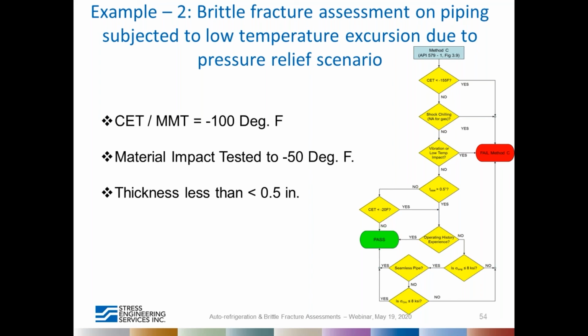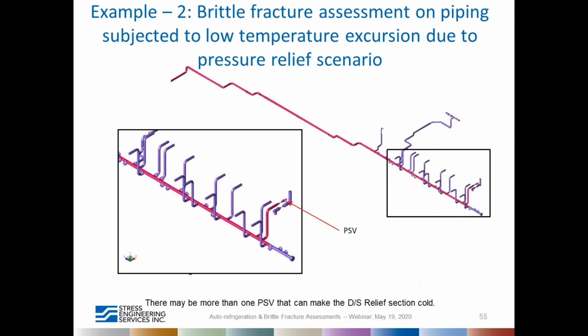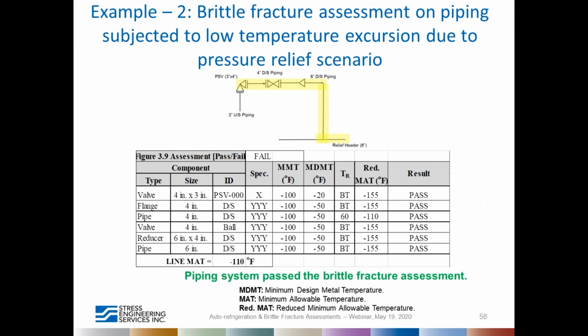However, even though this material is thinner than ½ inch, it does not qualify through Method C. So one has to do either a hydrotest-based assessment or a stress analysis-based assessment. Using stress analysis, you can model the system and then come up with the stress ratios and temperature reductions.